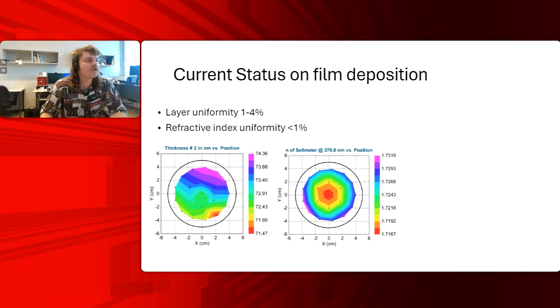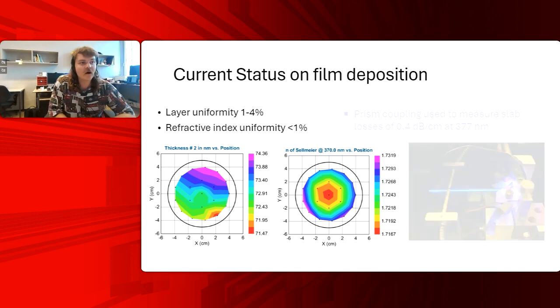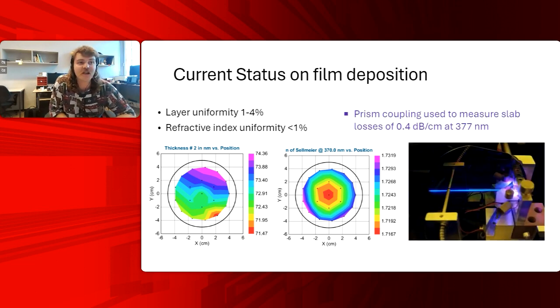After we're happy with the layer uniformity and refractive index uniformity, you can see a current state of our deposition allowing losses all the way down to 0.4 dB per centimeter at 377 nanometers. So this is already a picture that if you're familiar with silicon nitride technology, you can look at this and say, wow, there's no way silicon nitride would even operate that because it's below the band gap, and we can see the clear benefit of using this for UV operation.